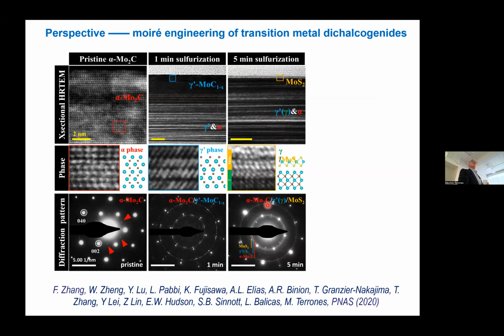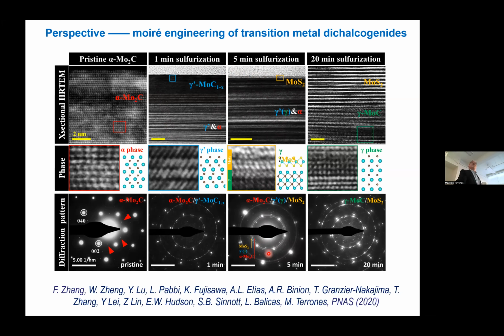And in the electron diffraction, we can see three rings. One of the rings belongs to the molysulfide, the other ring belongs to the gamma prime molycarbide, and the third one belongs to the alpha molycarbide. So we can see the three phases of the three different materials that we have there. Then after 20 minutes, when things are more thermalized, we have molysulfide and gamma molycarbide.